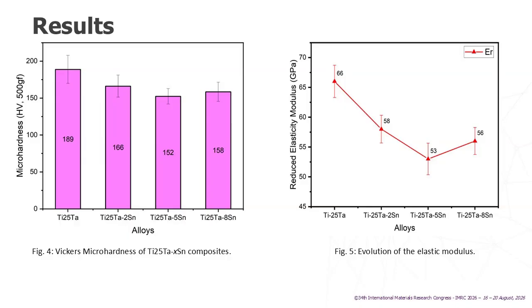The reduced elastic modulus test showed nonlinear behavior with a trend similar to that observed in hardness, where the titanium 25 tantalum base alloy recorded the highest value of 66 GPa due to the higher presence of titanium alpha phase. The addition of tin acts as a stabilizer for the titanium beta phase, which has lower structural stiffness, reaching its minimum value in the titanium 25 tantalum 5 tin composition, which has an elastic modulus of 53 GPa, since this point corresponds to the maximum retention of this phase.